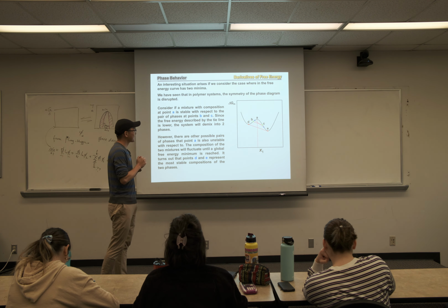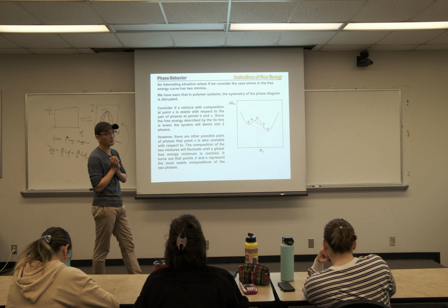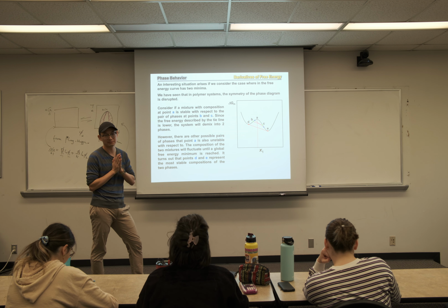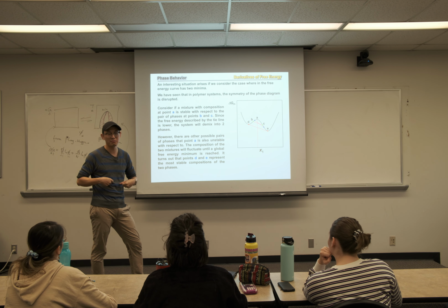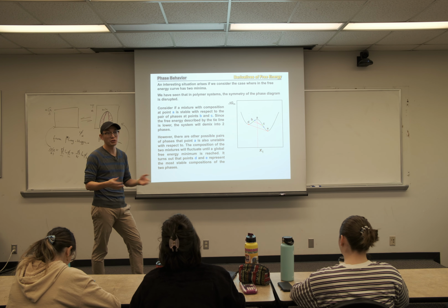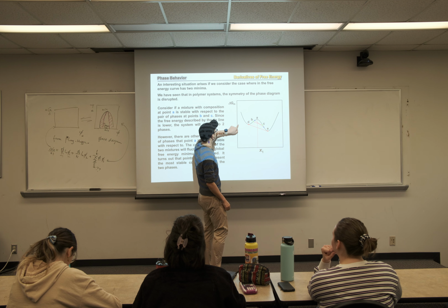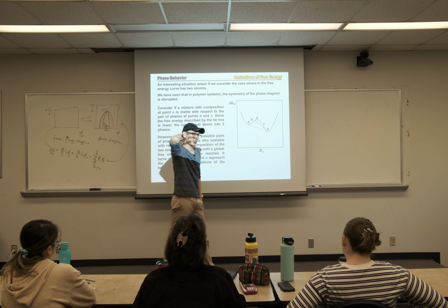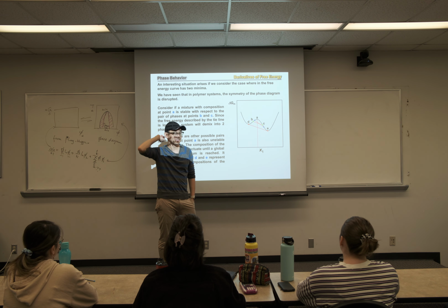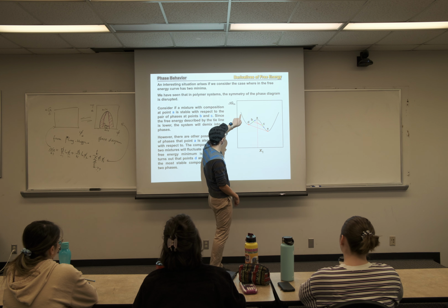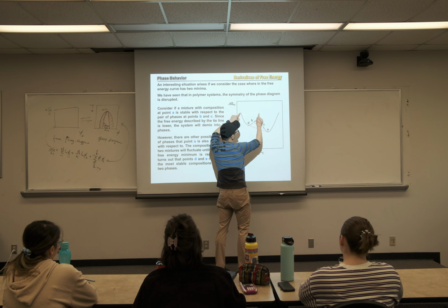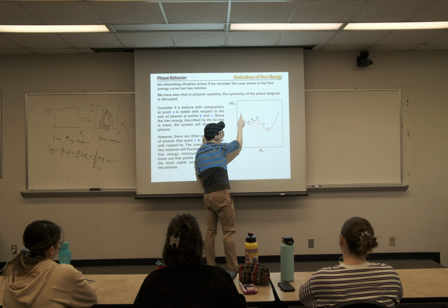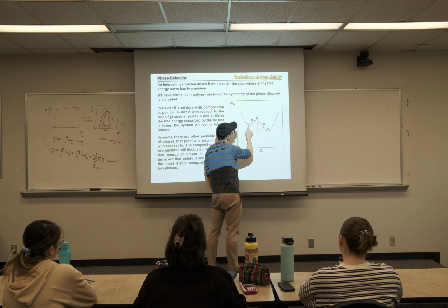by the system. So it turns out we just need to consider the lowest delta G the system can reach. When they phase separate, how much delta G can they lose? The more the better. But if we lose something like totally to zero here, this may not be the maximum loss of the delta G. Because if you lose to here and here, if you draw a vertical line, you start to gain entropy. So any phase separation needs to happen on these lines.